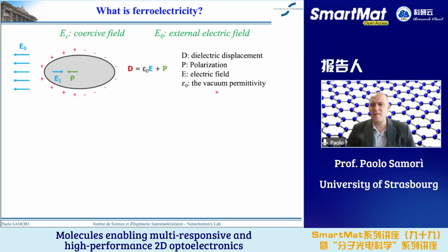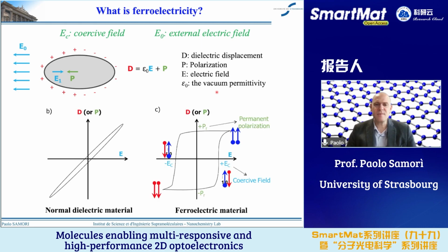And so the magnitude of the polarization vector depends on the difference between the applied electric field and the coercive field, and the number of memory states in a ferroelectric cell can be increased if you use the intermediate polarization state that you can obtain by applying an external electric field with magnitude slightly higher than the coercive field. So in this way, you can access different level states. And this is what you can observe here by sweeping the electric field.